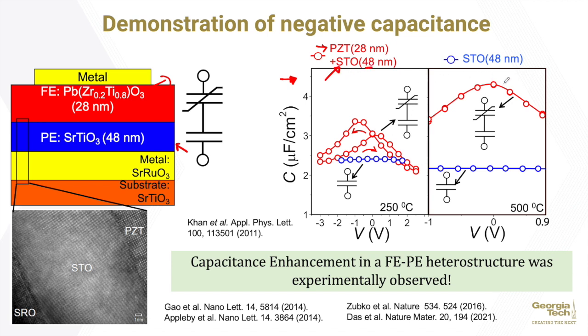And if we look at this, the total 28 nanometer PZT plus 48 nanometer STO capacitance is actually higher than the capacitance of the constituent 48 nanometer strontium titanate. And this essentially tells us that this 28 nanometer PZT ferroelectric was working as a negative capacitor. So this was first reported in 2011. It was reported for a higher temperature, but over the years, many other papers have reported similar behavior in a wide range of different materials and at room temperature. So that was the first experimental validation of this concept.